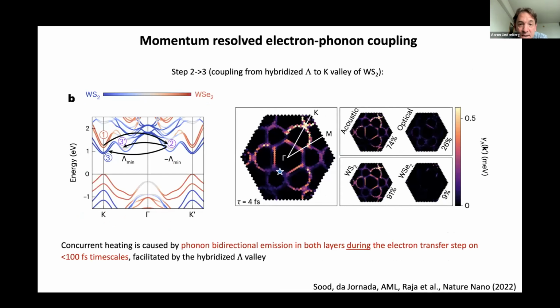And then the second step is the coupling from this hybridized lambda valley into both structures, giving rise to this bidirectional phonon emission. And again, one can compute the full momentum resolved electron phonon coupling processes directly, which supports this proposed model.